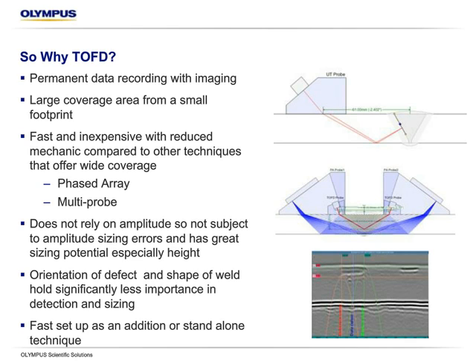Familiar with phased array, which Olympus also is in the business of. It also gives us a large coverage area, but TOFD typically can use very small probes, and because we manipulate that beam spread, we can get a very large coverage from a single set of probes and a very large amount of coverage from multiple sets of probes.